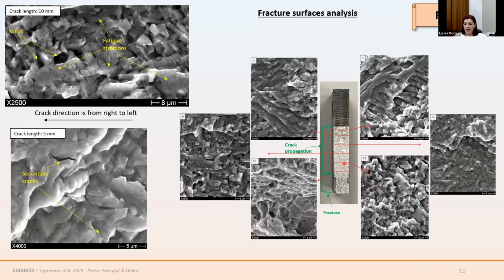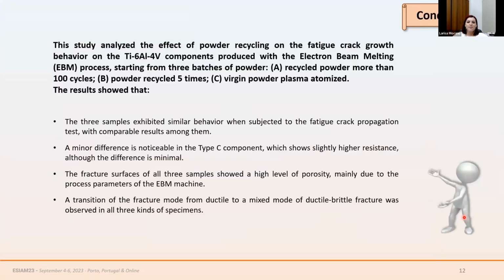approaching the area closer to the final fracture, there is a transition from this ductile mode to a mixed mode, brittle and ductile. But also in this case, this was observed for all the 3 kinds of components. So also in this case, relevant influence of the recycling processes was not observed.